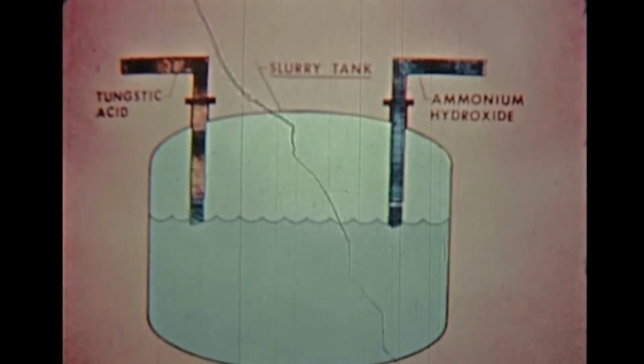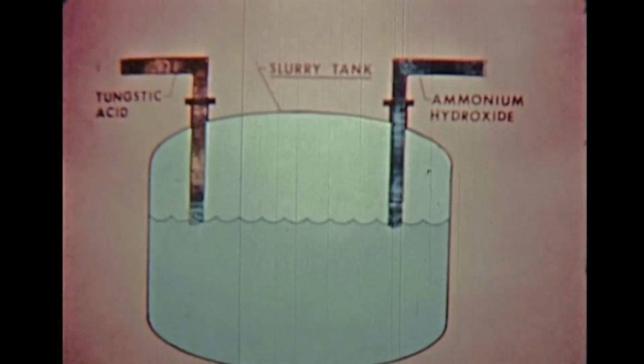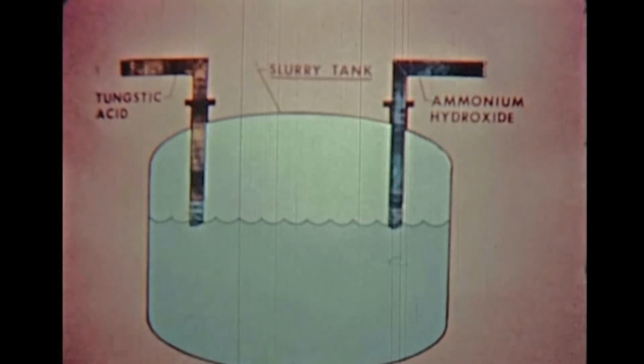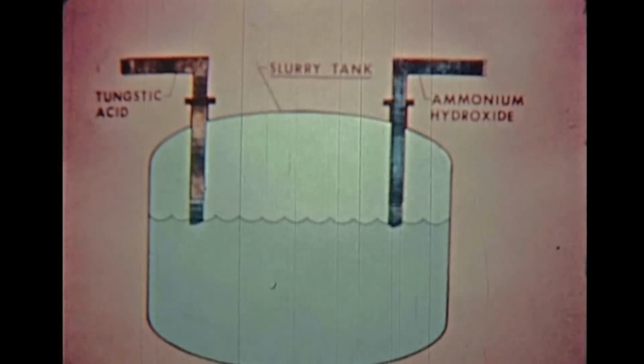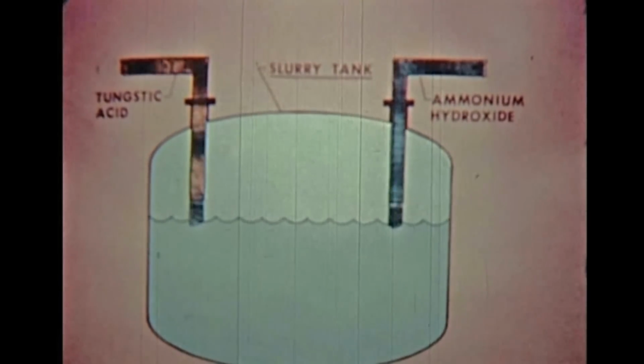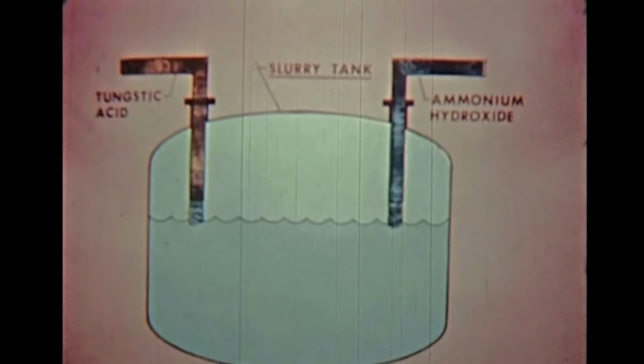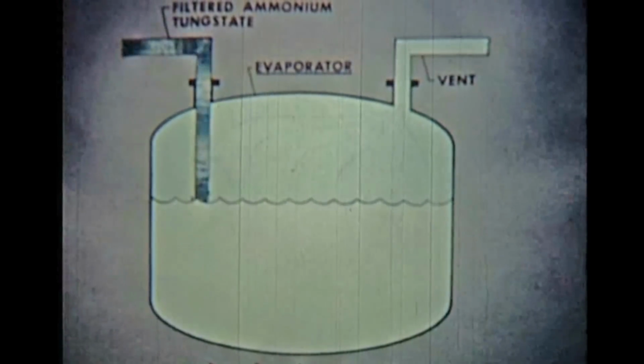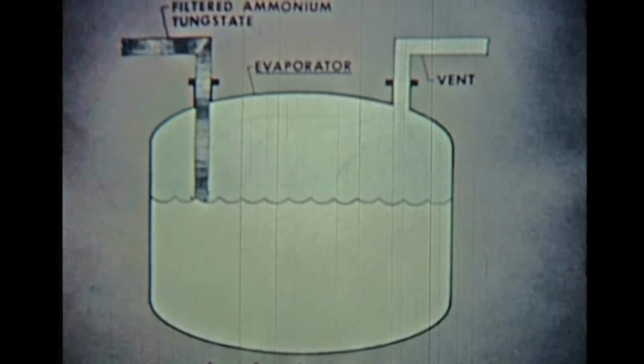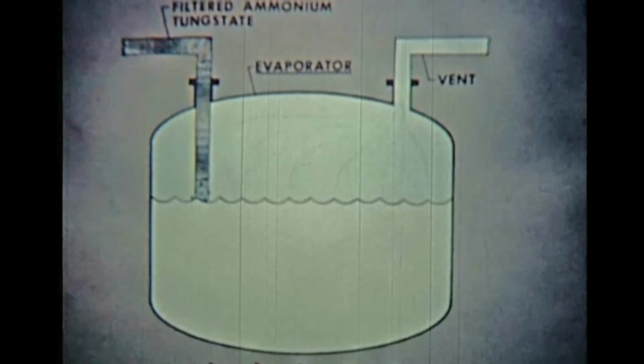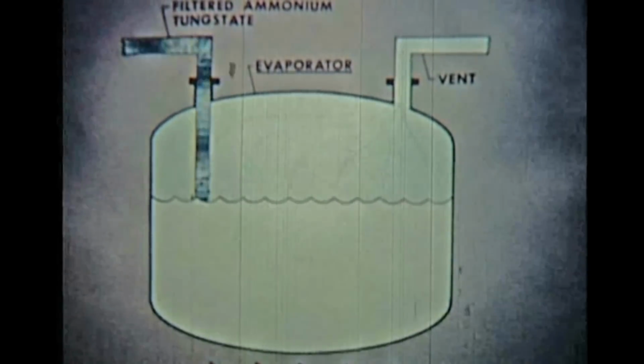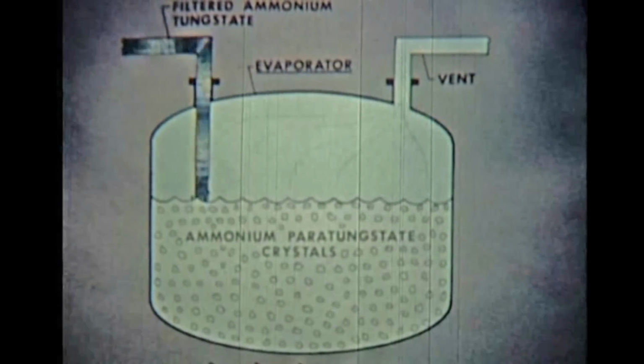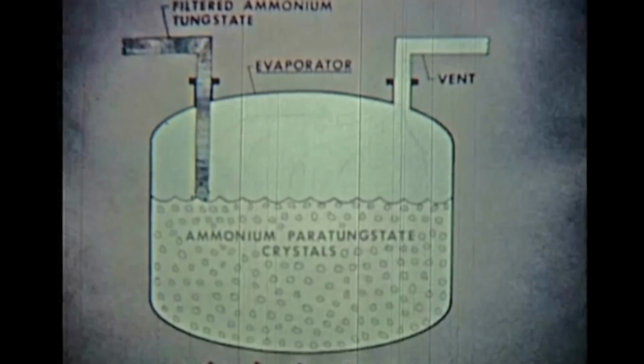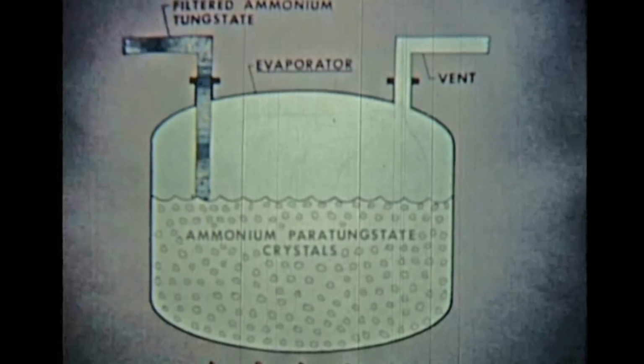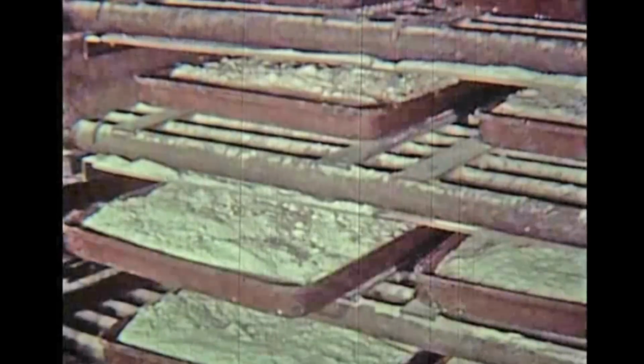The washed tungstic acid slurry is pumped into a tank with ammonia. The tungstic acid dissolves to form ammonium tungstate. This liquid is then filtered in the same manner as the sodium tungstate. The ammonium tungstate solution is heated to drive off water and excess ammonia. As a result, crystals of ammonium paratungstate form. The crystals are removed before all the liquid disappears and are washed and dried.